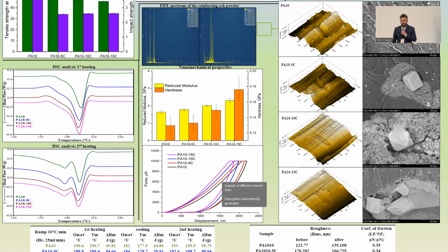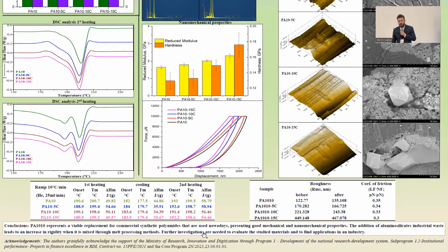resistant to scratches. And so we noted from this investigation that the introduction of ash powder in the polyamide 1010 through extrusion and injection molding leads to an increased rigidity of the composites. But also we require further investigations in order to improve other properties, such as the mechanical property, the impact strength, and the elongation of our final composites in order to find an application in some industry for these materials. And so I would like to thank you all for your attention.